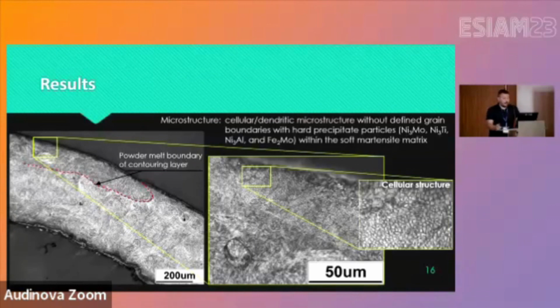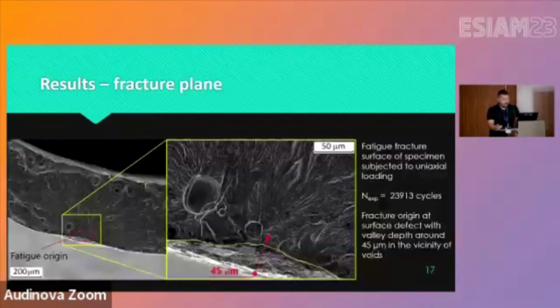So this is the SEM samples. You could clearly see the contouring and the hatching on the specimens, and the cellular structure with the hard particles within a soft martensite matrix. It can be seen here. Sorry, this is the same. And the cracks, like 90% were from the outer layer, mostly in imperfections, like the valleys here of roughly 45 micrometers. These were the places where the fatigue appeared.